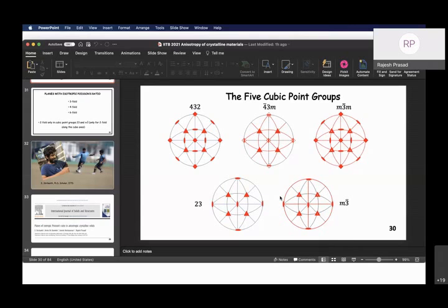But one student had asked, no? Yeah, there was a question about the mechanical properties, how much stress. The GPa question. I think because Young's moduli are in GPa, the tendency is to think that you have to apply something at the GPa level to measure. And the second thing is that most students, if you ask how these are measured, will say stress-strain test. They don't realize that ultrasound wave propagation is the way to measure these different elastic moduli. Yeah. Actually, elastic constants are rarely measured by these mechanical tests.